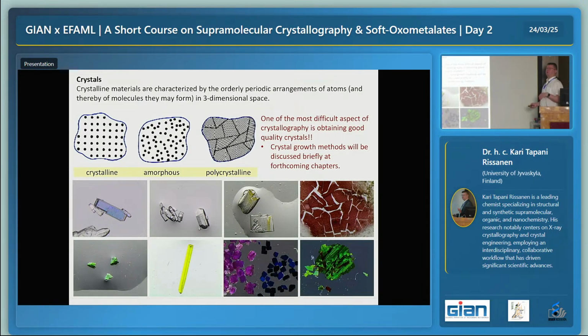So we can tell from the X-ray diffraction if our object is crystalline or not. And we can even tell if it's a single crystal. That will be later on. And that's the idea. We can then have an additional form, which is annoying for us. We call it polycrystalline. So it is like one entity, but it has domains. So here we have one single crystal. Here we have another, but they are in a different orientation. It's not the same. So you cannot go from here to here in the same way you can go from here to the next one.